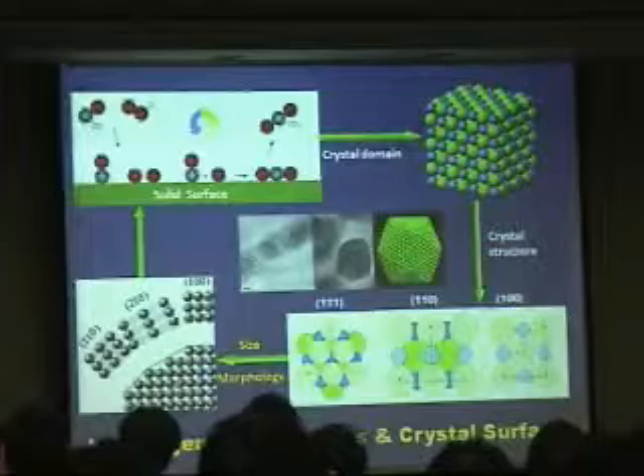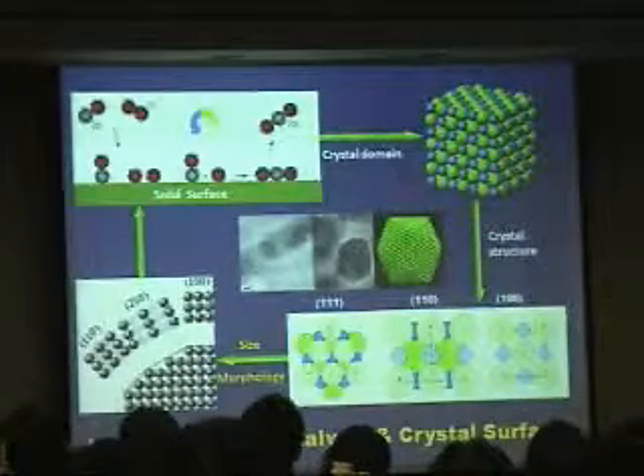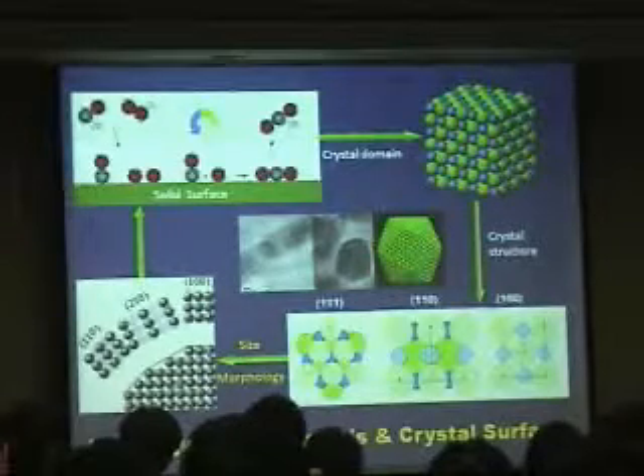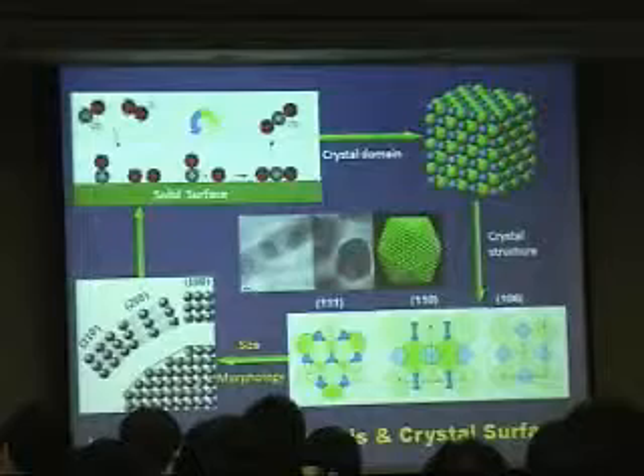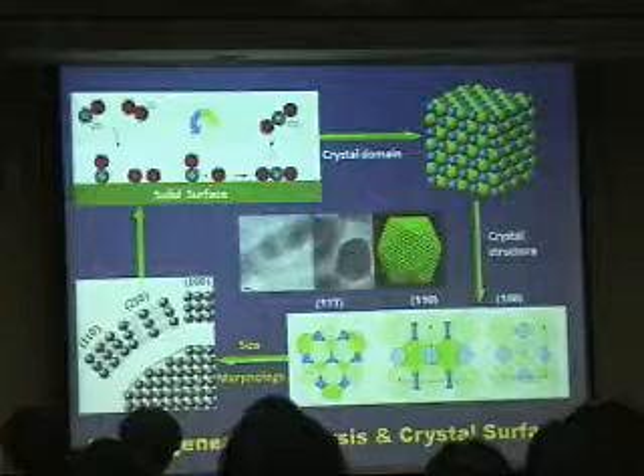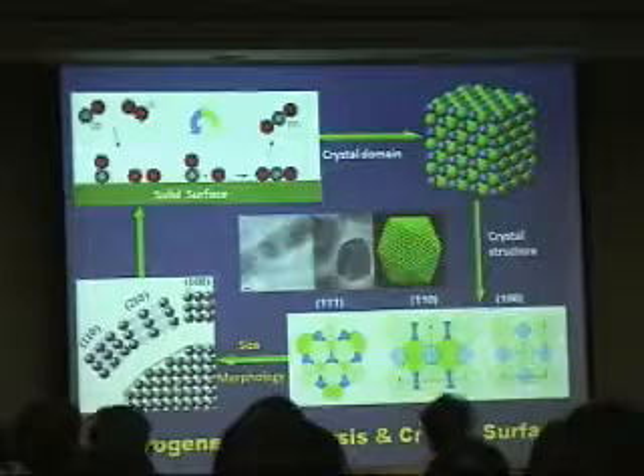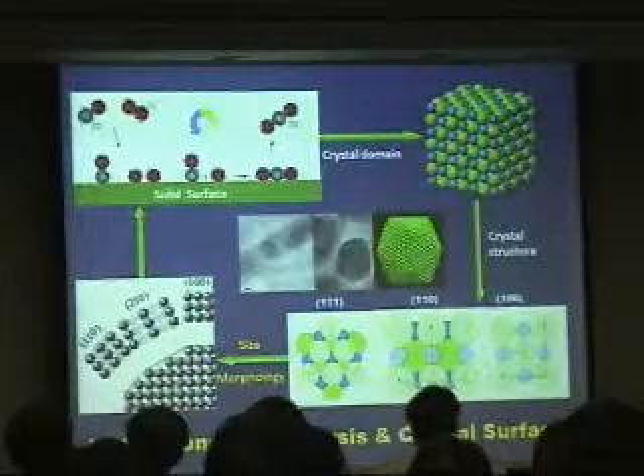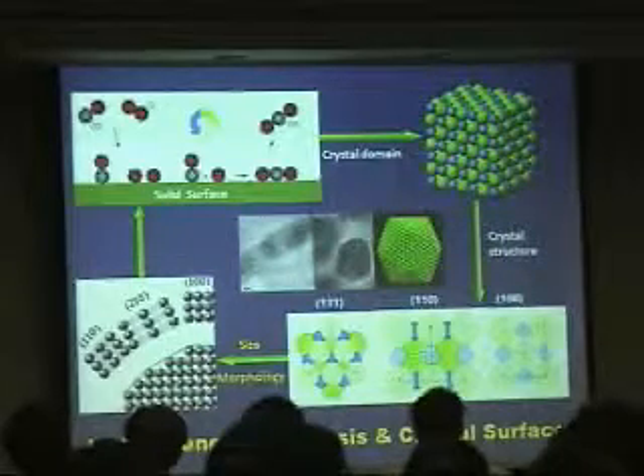Actually, if we go into more detail for catalysis, the reaction takes place on the surface of nanoparticles. So the shape and also the size of these particles determine their surface structure, more specifically, the coordination of the atoms on the surface. If the coordination is different, the chemical properties should be different, and that causes a large difference in the reaction performance. So there are at least two aspects that influence the crystal surface: the shape and the size of nanoparticles.